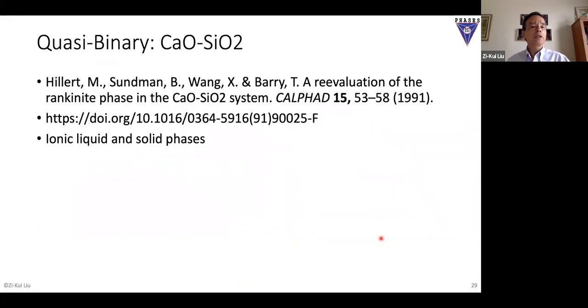All right, so the binary system. Now take a quasi-binary system, calcium and silica. So actually it's a ternary system, right? Calcium, oxygen, silicon. But however, if you cut through the calcium and silica line, then you actually get something that looks like a binary, because on that section, the oxygen partial pressure is fixed. So it's like a section at constant potential. That means the degrees of freedom just decreased by 1, so it behaves like a binary system.